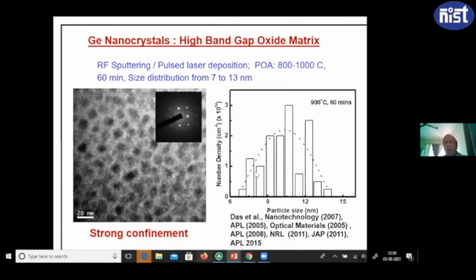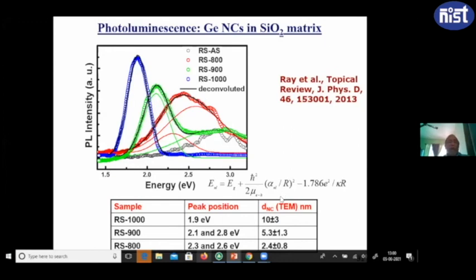That's what we wanted to show, and we published a lot of papers. So this was basically showing the number density of the germanium nanocrystals, and the average size is about 9 to 10 nanometer. Please remember, this size has to be lower than the de Broglie wavelength that I showed earlier. And since germanium has low effective mass, the germanium de Broglie wavelength is about 20 nanometer or so. So if you make it 10 nanometer, they are actually quantum confined. If you take different samples, you don't have to go into detail on that. What I want to show is that we get an optical emission intensity at different wavelengths: blue, green, and red.